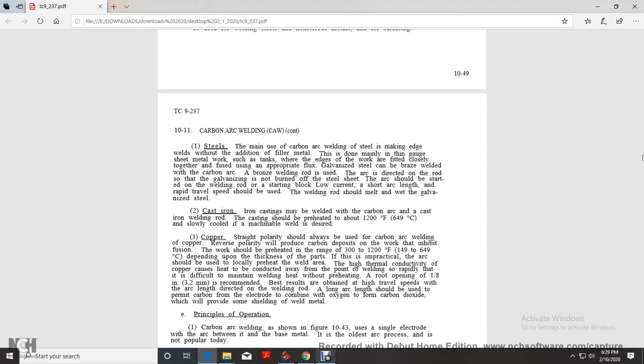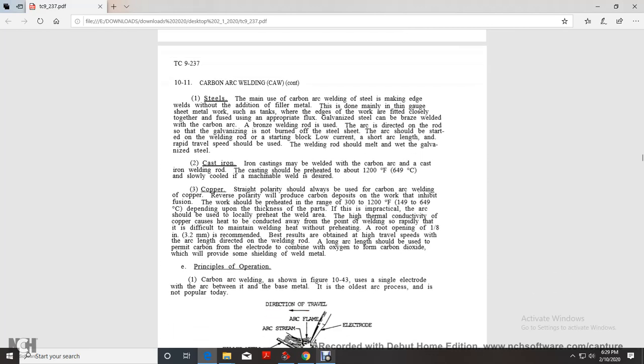that it is difficult to maintain the welding heat without preheating. A root opening of 1/8 of an inch is recommended. Best results are obtained with a higher travel speed, with the direction of the welding rod and a long arc length, which permits carbon from the electrode to combine with oxygen to form carbon dioxide, which provides some of the shielding of the weld metal.